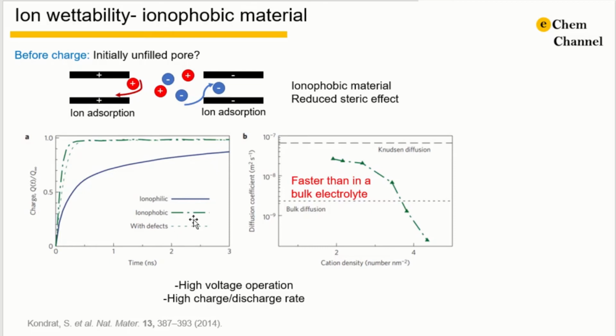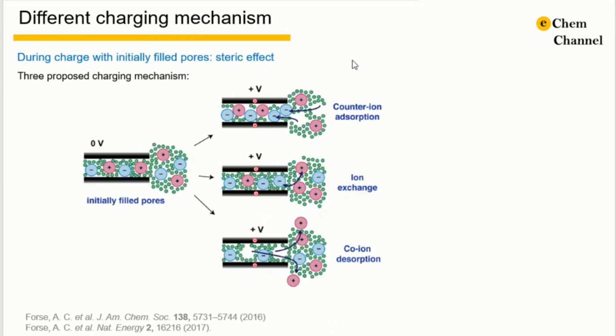Based on the simulation, the empty pores will start to absorb ions at a certain voltage. This voltage is usually high, and the diffusion of ions will be even faster than in a bulk electrolyte. In this way, a supercapacitor can realize a fast charge and discharge rate with a very high energy density. However, so far, no material shows ionophobicity, so we are still dealing with pores initially filled with electrolyte.